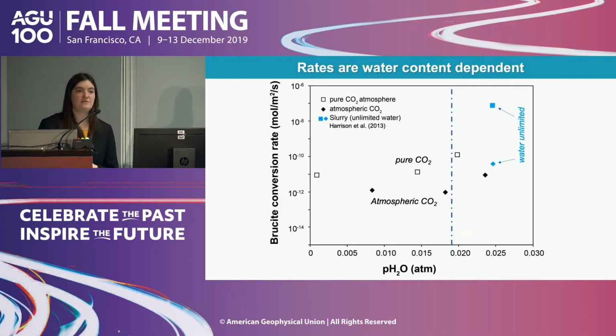But one of the things we wanted to get out of these experiments, ideally, was reaction rates as a function of water availability, so as a function of humidity in this case, with the ultimate goal that we might incorporate these into our reactive transport models to allow us to better simulate these conditions where we have low water. And so that's what's shown here, where we have the brucite conversion rate, so brucite going to magnesium carbonate, on the y-axis versus partial pressure of water on the x, where again we observe this thresholding effect. So our atmospheric CO2 experiments are shown by the black diamonds, and pure CO2 by the white squares. And in both cases, we see below this threshold low overall rates of reaction that are essentially independent of humidity. When we reach this threshold, our reaction rates increase.